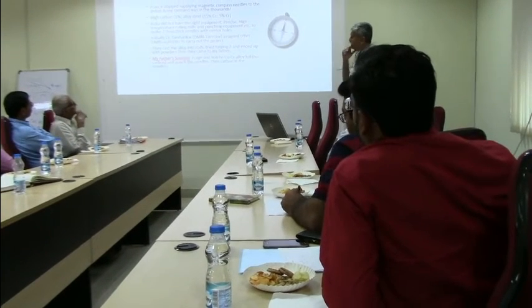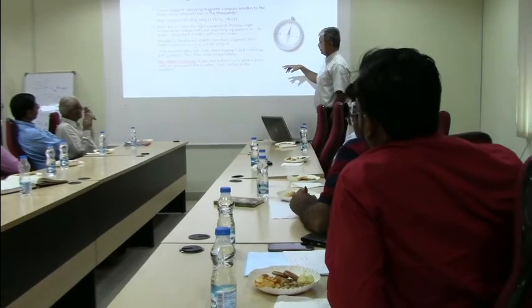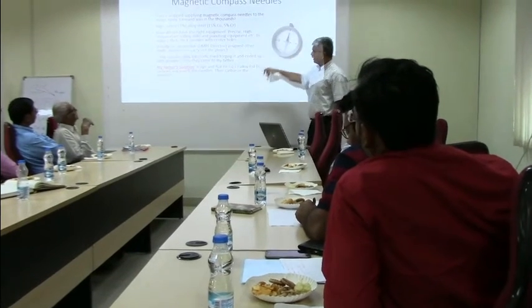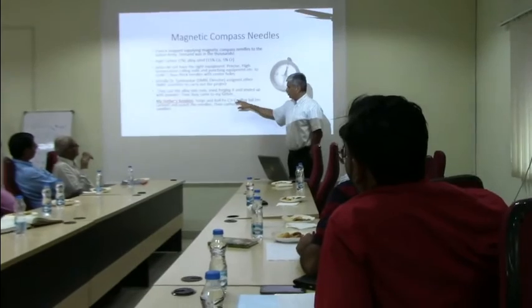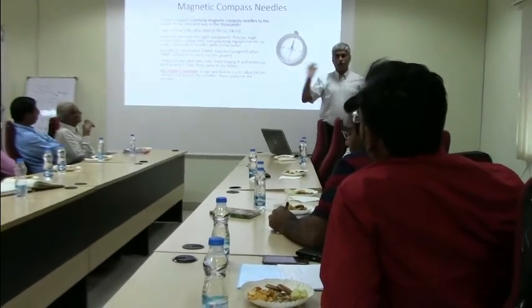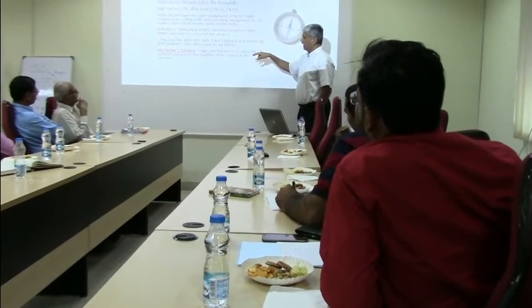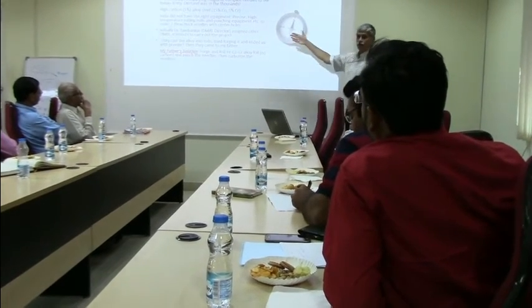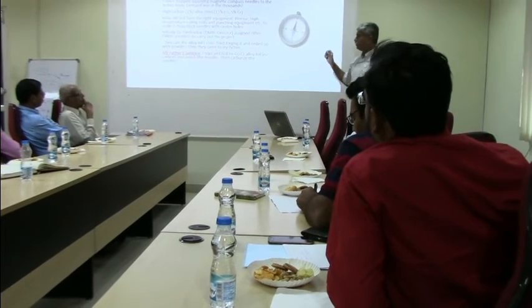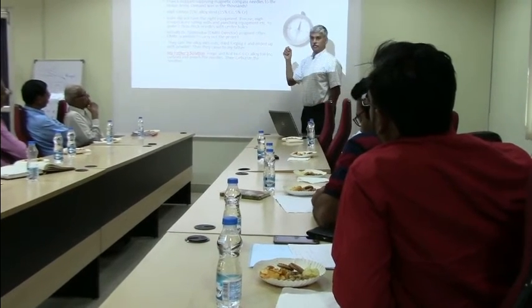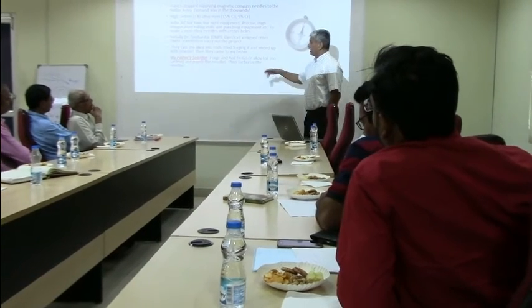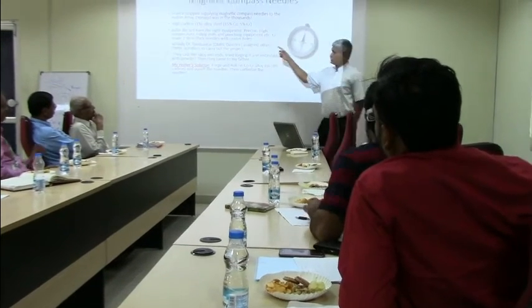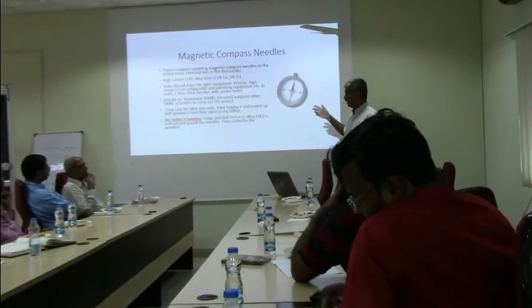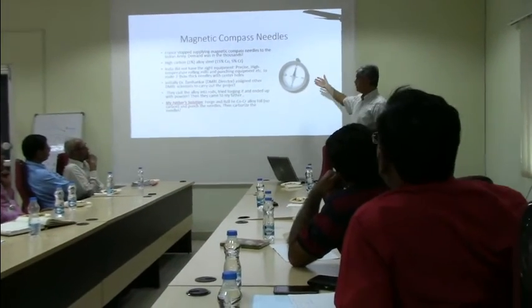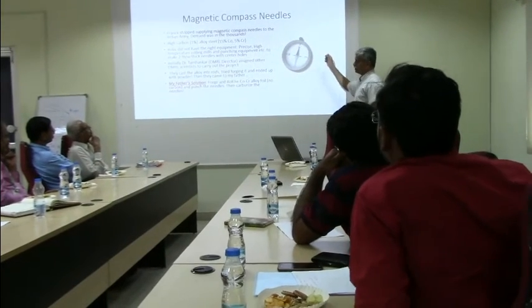My father's solution was kind of innovative. He said, don't put the carbon in, just take the iron cobalt chromium alloy, and that you can roll because it is very soft, and you can make it into an alloy foil down to 2 thou. Then you carburize it. And the carburization thickness is about 1 mil. It limits itself at 1 mil. So instantly you get the 1% carbon composition that you wanted, but you've also managed to make thin foils and been able to punch the needles.